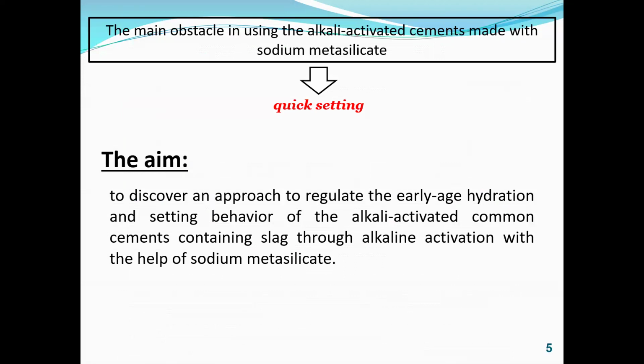The main obstacle in using the alkali-activated common cements containing slag made with sodium metasilicate is a quick setting. The use of setting retarder, effective in alkali-activated cements, for example, sodium lignosulfonate, can be a way to control their structure formation processes. So, the aim of the study was to discover an approach to control the structure formation in alkali-activated common cements containing slag through alkali activation with the help of sodium metasilicate.